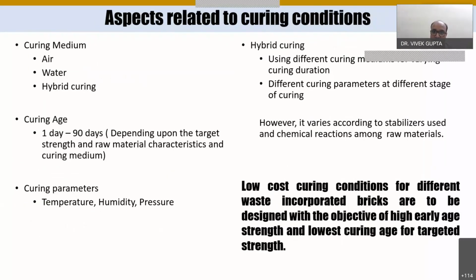Then these are the different aspects of the curing conditions, like the curing medium: air, water, and hybrid curing are trending nowadays. Then the curing age, 1 day to 90 days. And then these are the curing parameters: temperature, humidity, pressure. So hybrid curing is nothing but using different curing mediums for varying curing durations. Let's say, for the first 4 hours they put it in ambient air, and after that they put the wet cloth for 7 days, and then they pour in water for the next 21 days. So that can be considered a hybrid curing method.